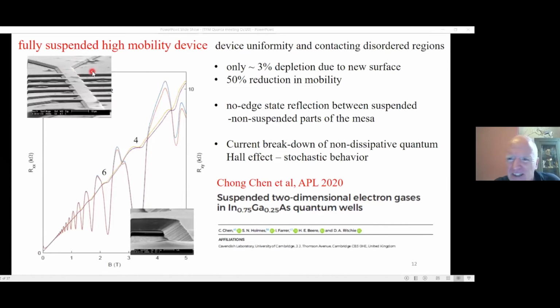If we're in the high mobility limit, this is actually a slightly thicker layer. This is a gallium arsenide layer, just for comparison. This is a freestanding gallium arsenide layer here. This is all freestanding. Everything that you can see there is freestanding above the substrate. It's thermally anchored at the ohmic contacts, but here it's just freestanding. We see very, very clear quantum transport. This is not in the disordered regime now. This is just a comparison.